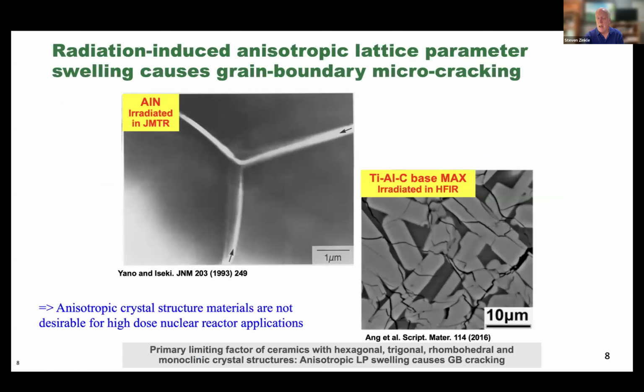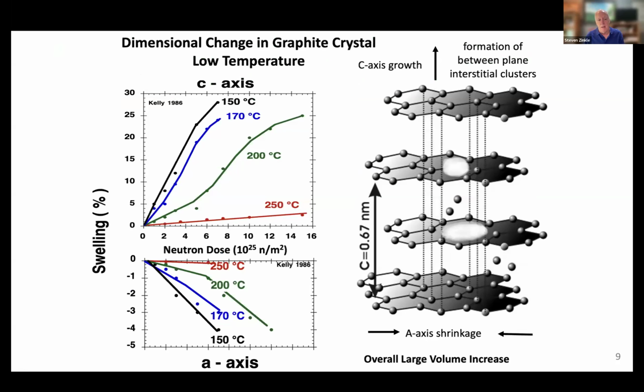Many of the candidate ceramics are non-cubic systems, or hexagonal or other anisotropic systems. Under high fluence neutron irradiation, these systems are susceptible to grain boundary microcracking. A few examples are shown here, where you can see the pronounced cracking that occurs in these systems. And that's inherently due, at this intermediate temperature regime that I mentioned previously, to differential swelling along the different lattice directions in the grains of the material.